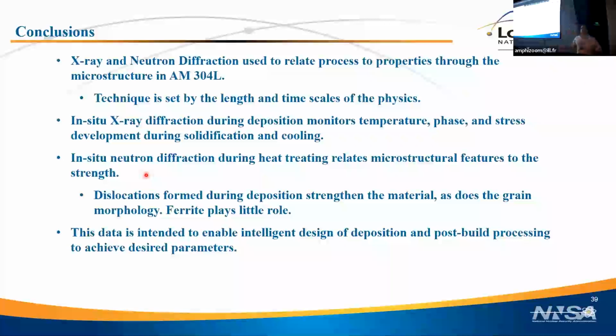What I hope I've been able to show you is that neutrons and X-rays, both of them are very effective at monitoring microstructure, but you have to be careful. You have to understand your assumptions. You have to know how to separate and deconvolute all the different microstructural features that might affect a given diffraction pattern in a given way. Whether you choose to use X-rays or neutrons is very much set by the time scale you want to measure and the length scale of what you want to measure. If you want to measure something big, use neutrons. If you want to measure something fast, use X-rays. But by all means, use the right tool. Even if you have an X-ray machine in your own laboratory, when neutrons are the right tool, use the right tool, and vice versa.